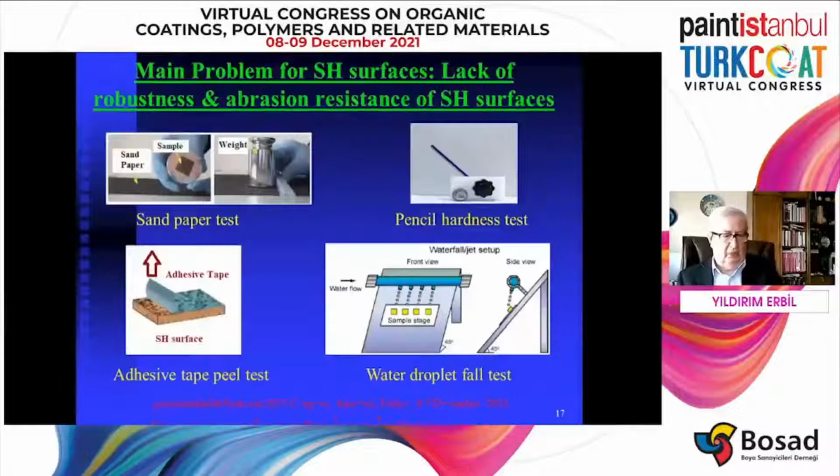Now, in this part, I will talk about the main problems of superhydrophobic surfaces, which prevent them from being applied in industry. Patterns containing needle-like structures are ideal to obtain a superhydrophobic surface, but they have very poor abrasion resistance. Small mechanical forces can destroy the texture on a superhydrophobic surface having micrometer or nanometer sized structures in the natural environment.